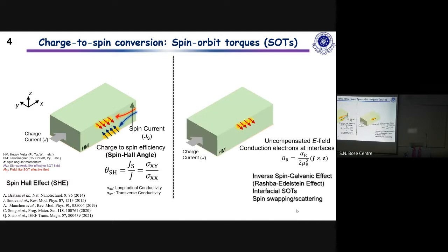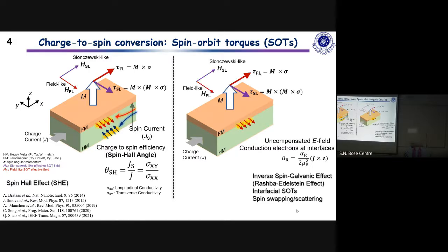Apart from that, there is also another effect which coexists along with the spin Hall effect in most of the systems, and that arises from an uncompensated electric field across the interface. This is mainly called the Rashba-Edelstein effect. But the net consequence of both of these effects is more or less the same, where you have an accumulation of spin angular momentum at the interface. So when you have a ferromagnet or an antiferromagnet on top of them, this spin angular momentum can be absorbed by the magnet, and then it can give rise to torques acting on the magnetization. This is called spin-orbit torque. You apply a current, and this electrical current exerts a torque on an adjacent magnet. It was understood that if it is strong enough, it can actually cause reversal of this magnet.